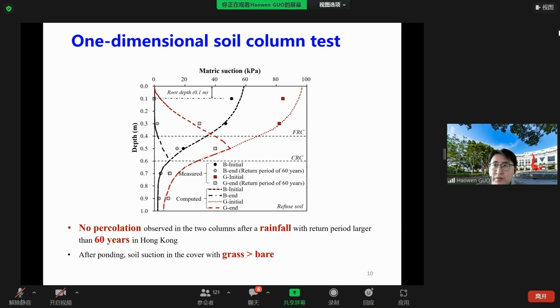This slide shows the measured and computed variation of matric suction in those two columns before and after ponding. The numerical results match the measured results reasonably well. We can find that before the ponding, the initial suction in the grass column is larger than that in the bare one. This is mainly due to the evapotranspiration-induced root water uptake in the top layers. The high initial suction corresponds to lower permeability. It can reduce the water infiltration during the ponding.